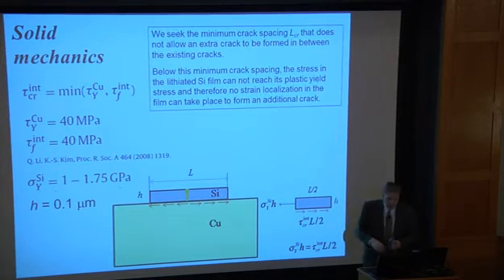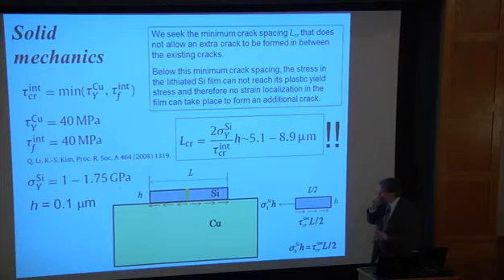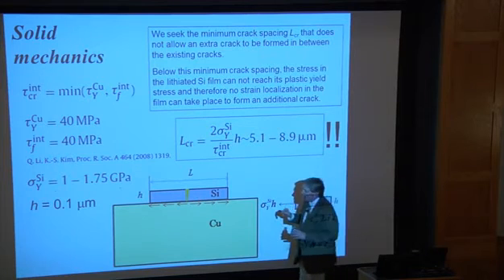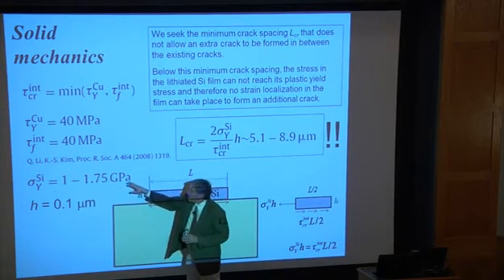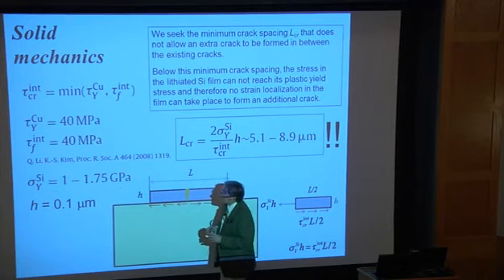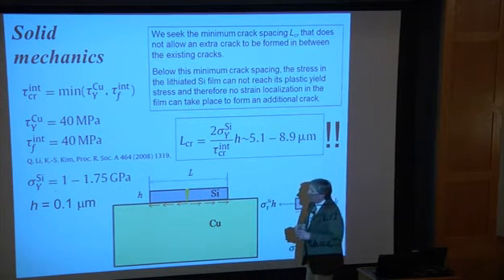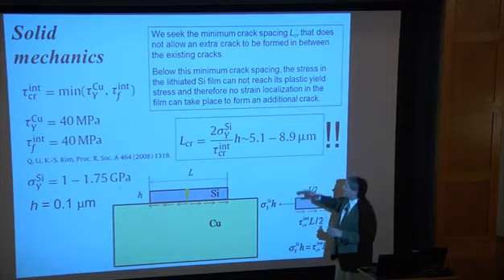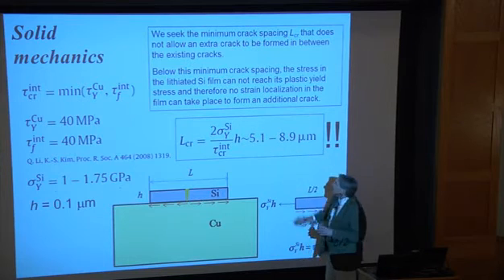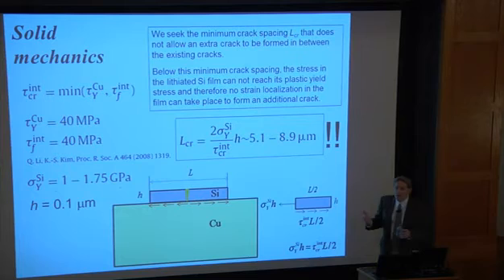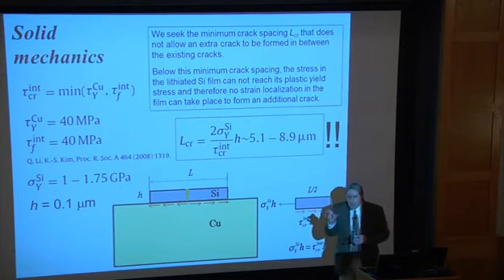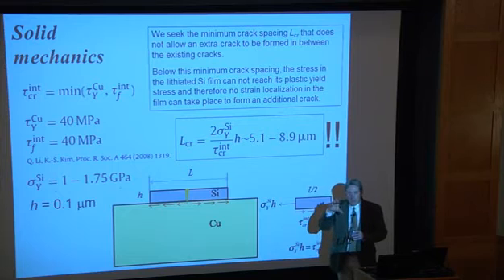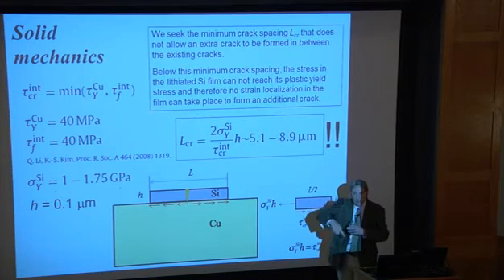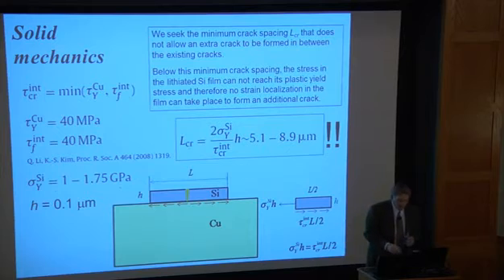And you can actually do a very simple force balance on these systems, which is one of the things we did. And there are some published values independent of this work for the yield stress of silicon and the interfacial flow stress for silicon over copper. And what you find is, fortuitously, you come out in about the 5 to 9 micron region, which is quite surprising. We were at 7 microns and we saw good stability. The point is, you do get a size effect in these systems. Now, remember, we're dealing with very thin films. If we had thicker films, now we'd have problems in our dimension normal to the film as well for stability purposes.